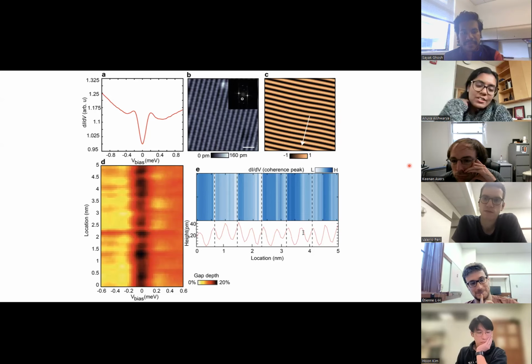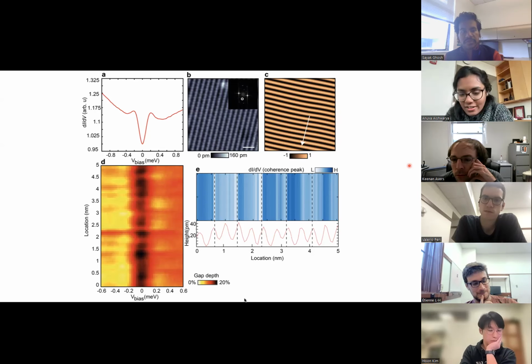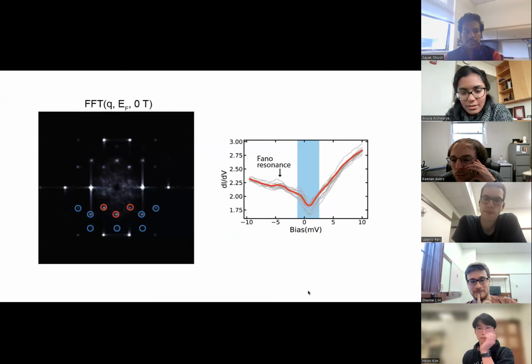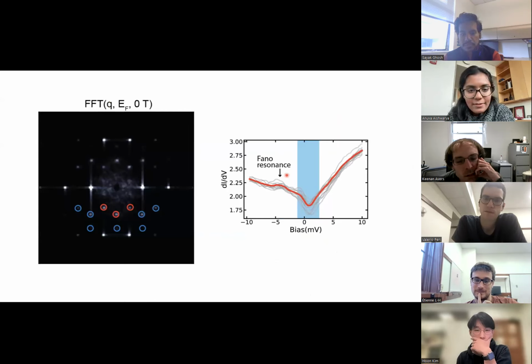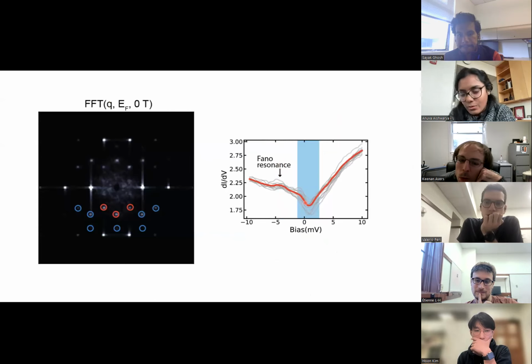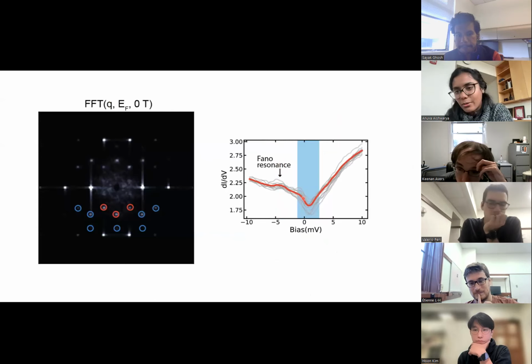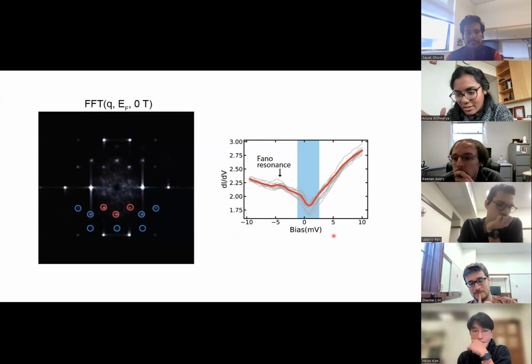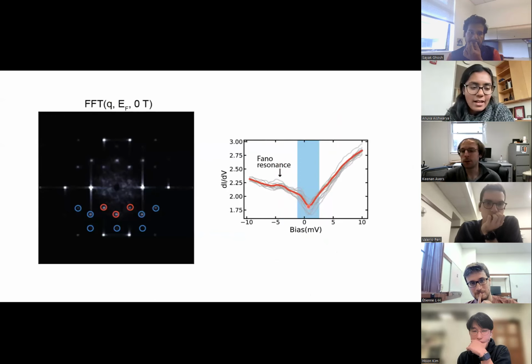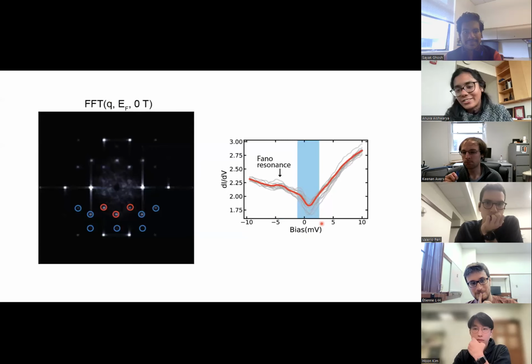We do see some strange feature in spectra at an energy scale which would agree with the, so this is the Fano resonance at minus 6 or 5 meV, but there's this change in slope around minus 1 meV, minus 1 to minus 0.7 meV, which would kind of agree with the temperature scale of the CDW, 6-7 Kelvin. But honestly, we see the CDW across this entire range. So at every energy slice, the density of states oscillates. So I don't know. I don't have a good answer for you.